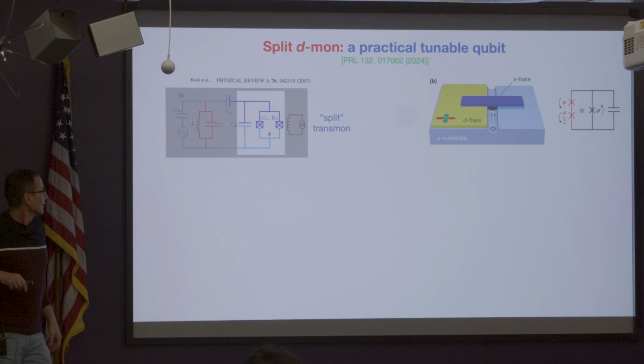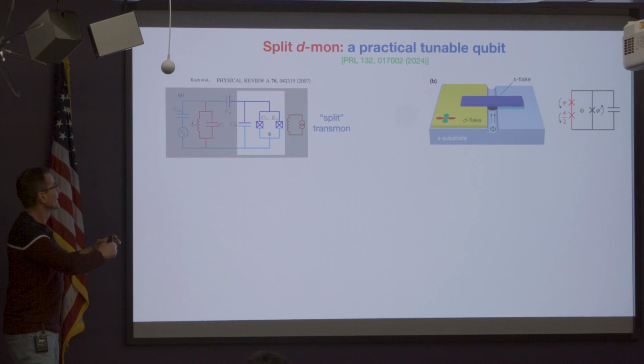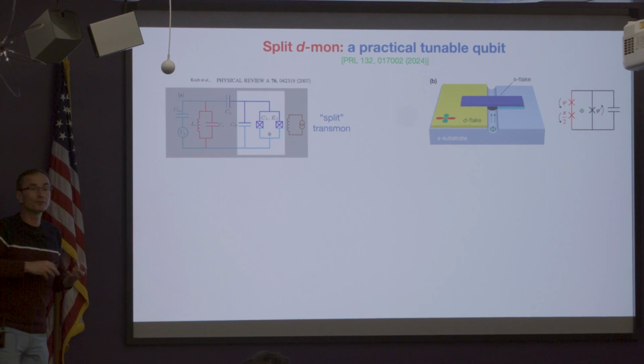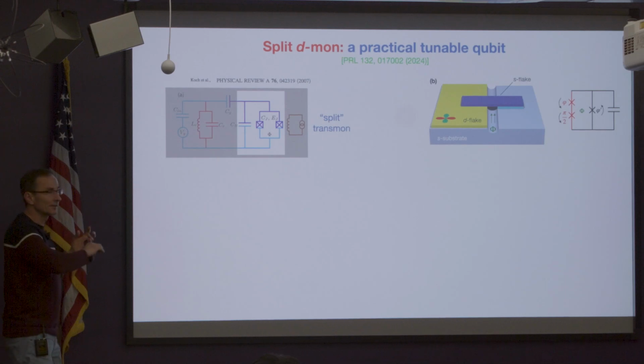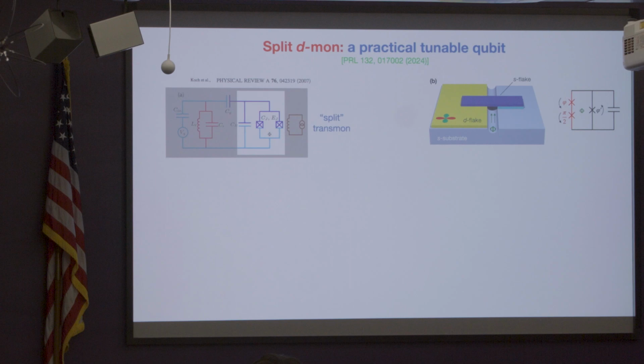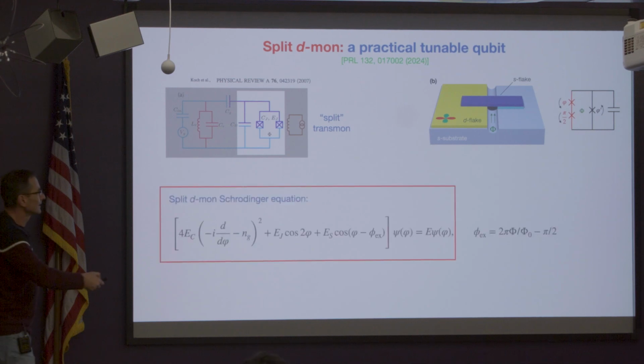Basically, the reason is this: when you fabricate a single Josephson junction, by fabrication you can to some degree control its energy because it's proportional to the area, for instance. But this will vary from one junction to another, right? So if you want to have a really specific value of your Josephson junction energy, the way you do that is this trick where you put two junctions in parallel and then put a magnetic flux in it through some nearby wire that produces a magnetic field. And it turns out those two act as a single Josephson junction with a junction energy that is tunable by this flux. And it's a simple calculation which I will not reproduce here, but you can find it on page 2 of any book on quantum computing. So that's exactly what we do here.